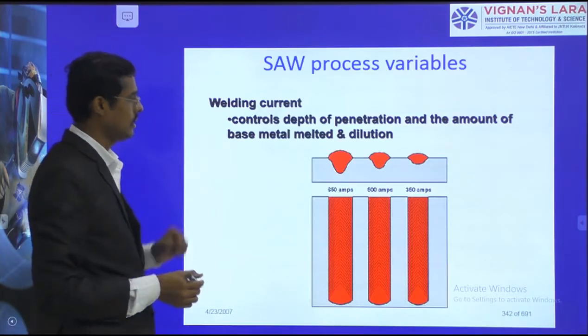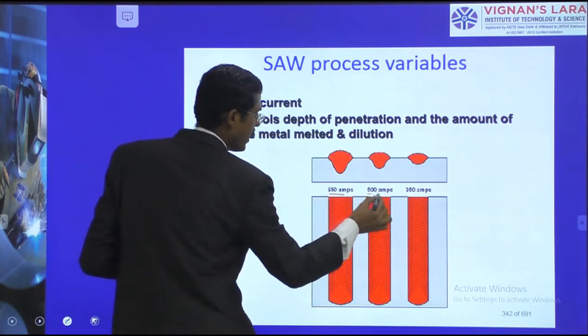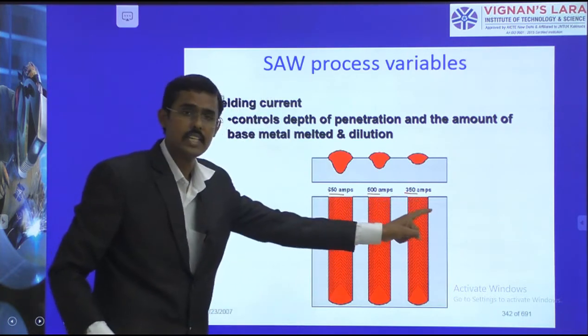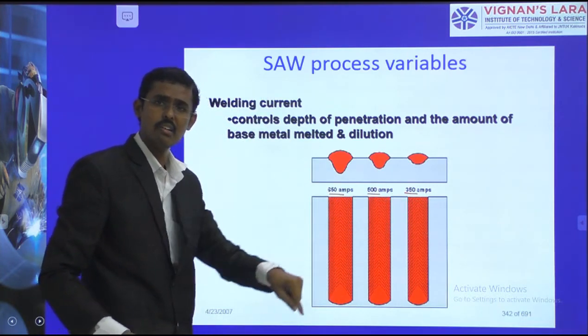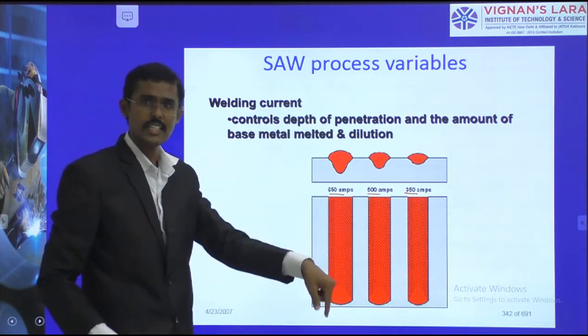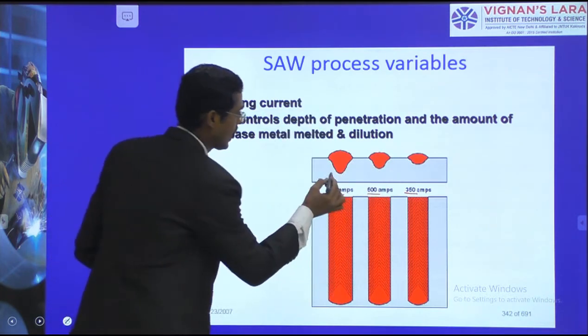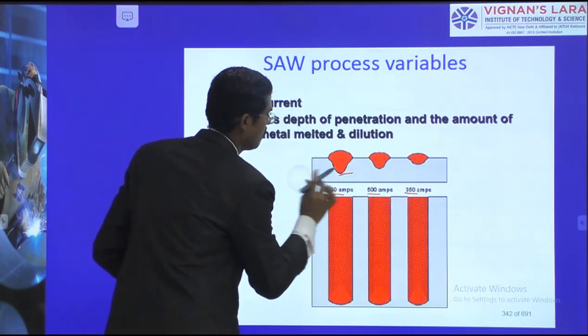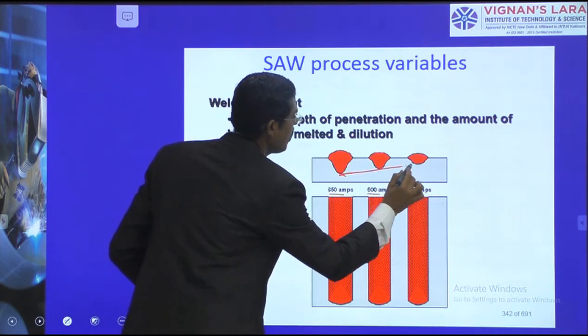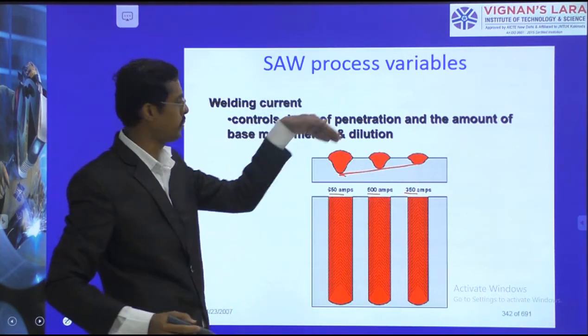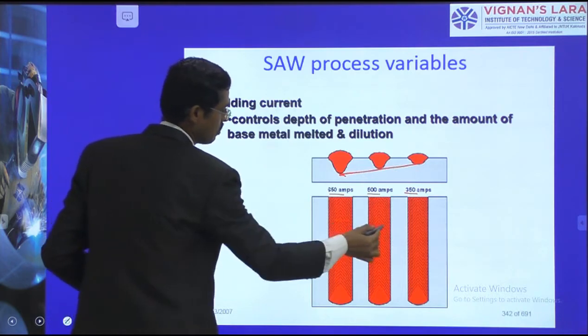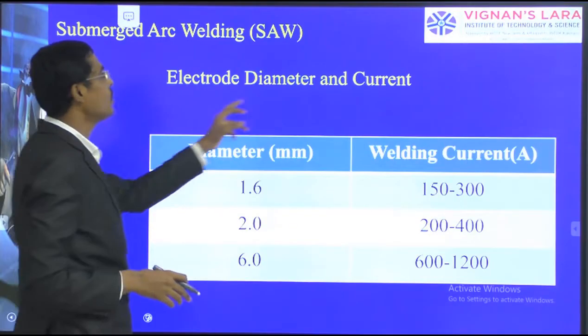So the welding current 650, 500 and 350. As the current decreases, the bead also decreases and penetration also decreases. See, here it is high current. When we go for low current, it keeps on decreasing. You see, it keeps on decreasing. The penetration does not happen. Similarly, width also. So the electrode diameter is there.